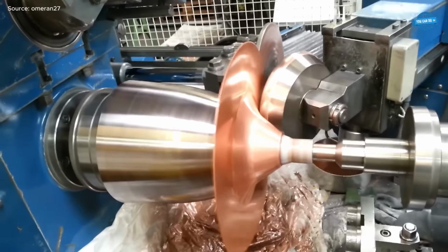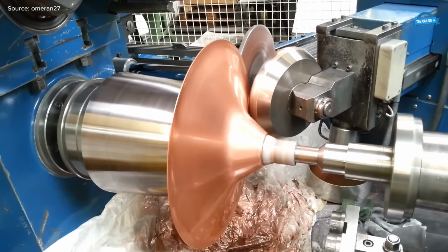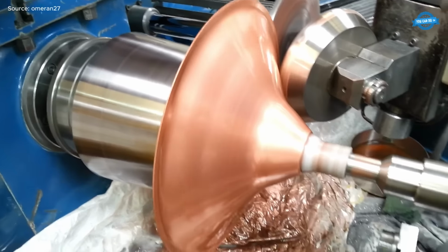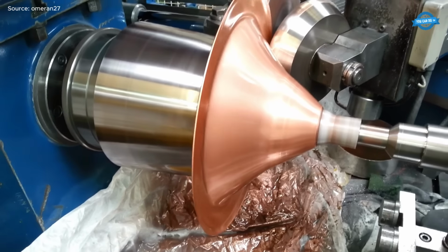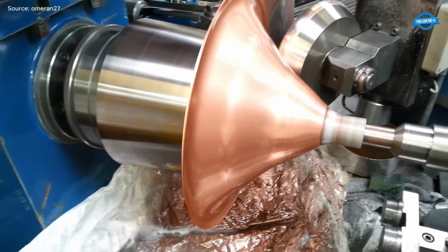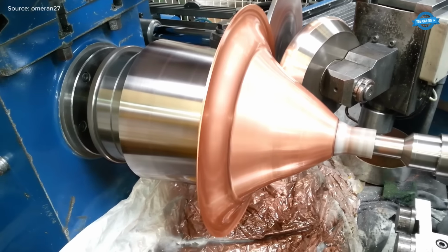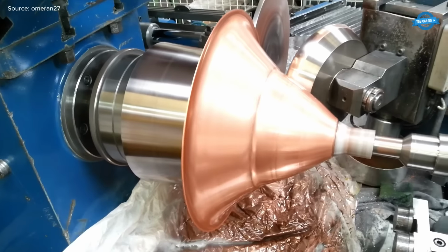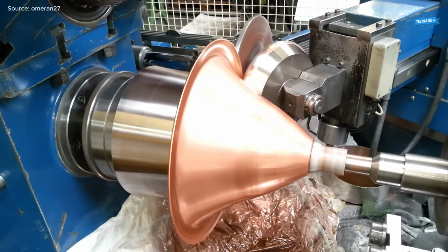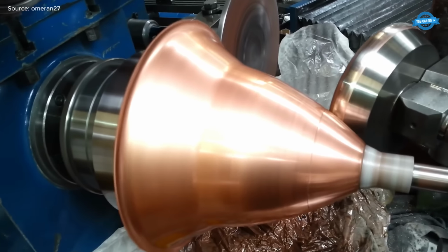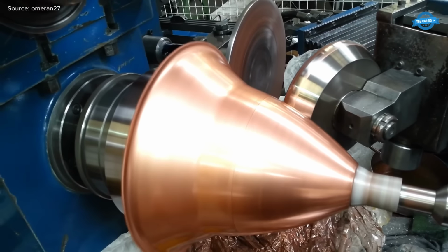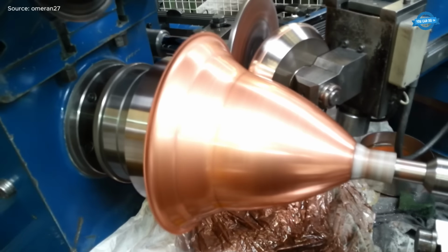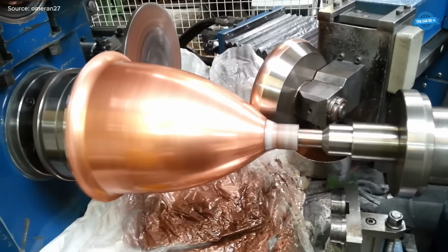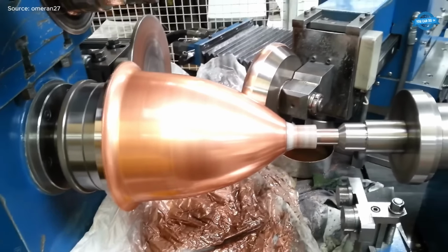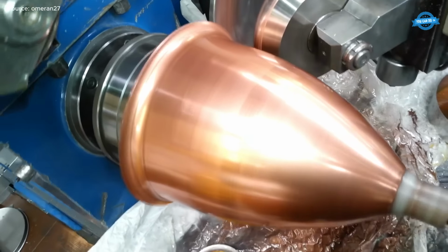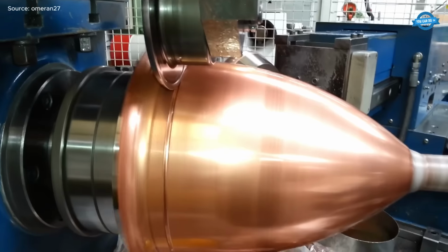Metal spinning is a precision forming technique used to produce hollow, asymmetrical components from flat metal discs. The blank is clamped onto a rotating mandrel and spun at high speed, while a hardened roller tool progressively applies pressure to shape the material along the mold profile. This cold forming process maintains material continuity, improving strength and reducing waste compared to machining. It is ideal for thin-walled parts, delivering high-dimensional accuracy, smooth surface finish, and efficient production of components such as cones, cylinders, and complex curved geometries.